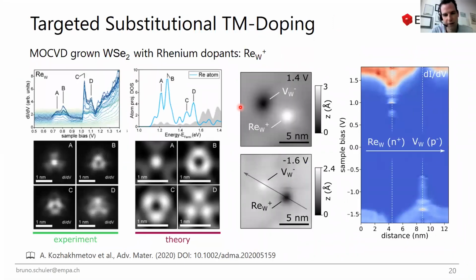Now, something we have looked into more recently is to use bottom-up synthetic means, to introduce different transition metals during the growth of these materials, such as, for instance, rhenium. Here, our Penn State collaborators introduced rhenium dopants into this material, and it's very nice because you exactly know what you put in there. So the assignment is almost becoming trivial if you compare it to the ones which we don't know a priori. We can do again also the FT. We see a beautiful match between the chemical defect orbitals and the ones which are calculated.